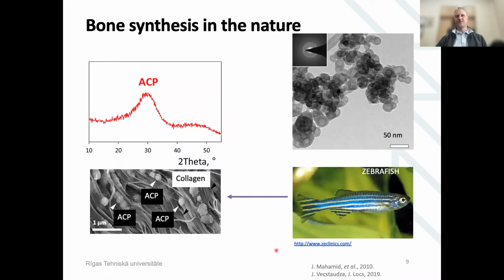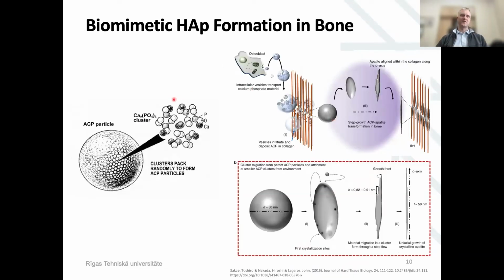scientists, Mahamid et al., found out in the zebrafish that there are some small calcium phosphate particles, but they are not crystalline, as we usually make in the synthesis of hydroxyapatite. They are amorphous. And this is an X-ray diffractogram that shows the amorphous state. And here is also the size of the particles. And this made us aware: why do we work with hydroxyapatite? Let's try to work with amorphous calcium phosphates. So what are amorphous calcium phosphates? These are very, very small calcium phosphate clusters that are then organized into amorphous calcium phosphate particles.